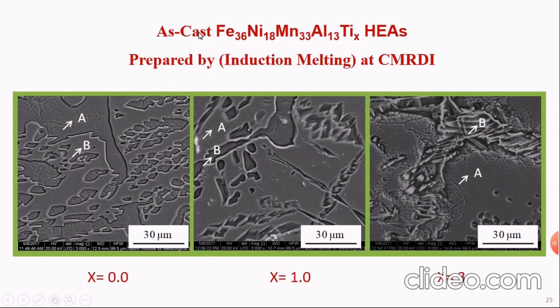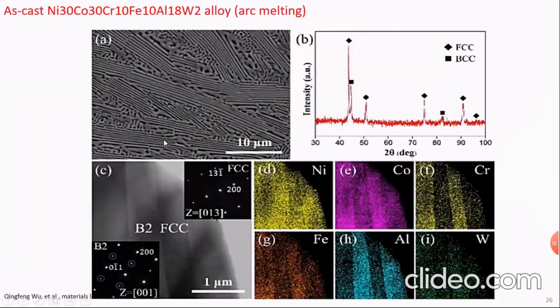These are examples, for example, as-cast iron, nickel, manganese, aluminum, titanium high entropy alloys. These percentages are in weight percent, not atomic percent. This alloy was prepared at my institute by induction melting, by repeating the induction melting process. This alloy has two phases, which change in their percentages in the microstructure according to the titanium addition. This was 0 titanium, 1 titanium, 3 titanium. And here, as you see, you have solid solution of two phases.